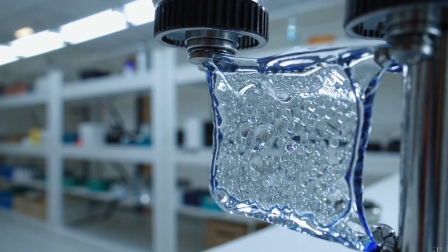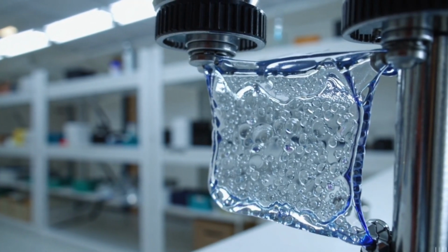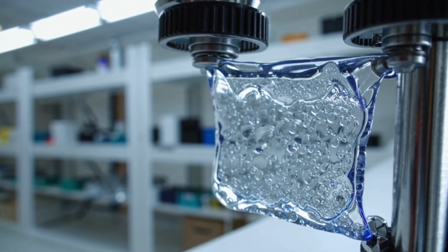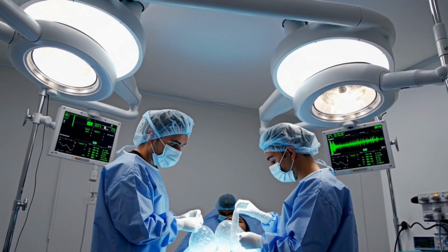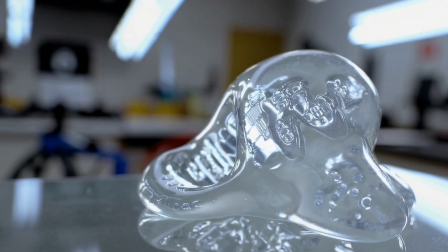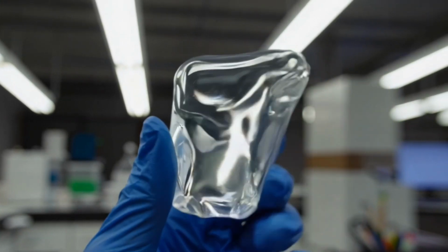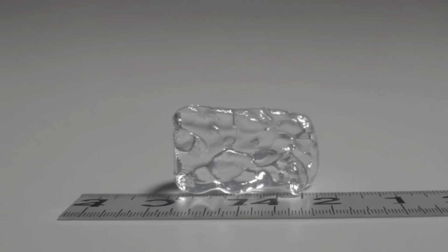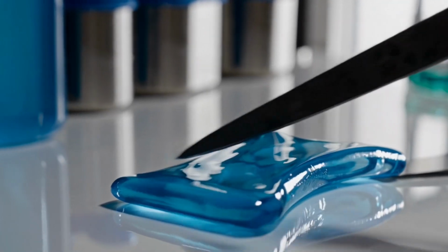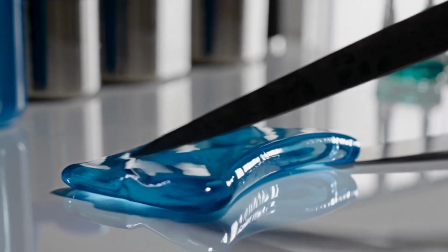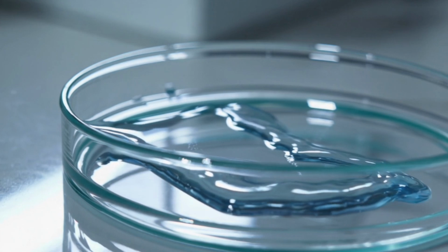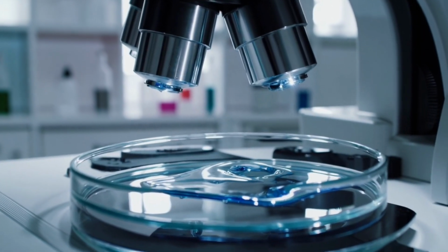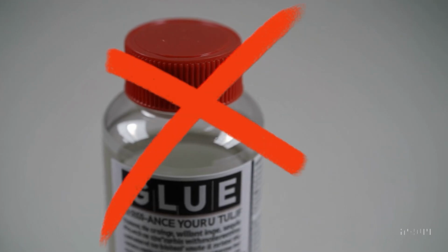Under tension, it reaches an ultimate tensile strength of 4.2 megapascals before snapping, enough to support heavy loads for implants or soft robots. And it does this while remaining flexible enough to stretch over 200% of its length. Cut it and let the pieces touch again, and the gel heals itself. In an end-to-end test, it recovers about 33% of its original strength within 48 hours, no glue or heat required.